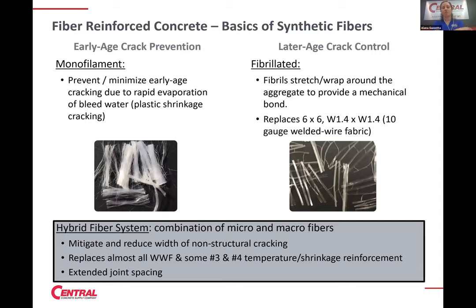These are things to look at in terms of weighing the options of putting synthetic fibers in a concrete mix versus having rebar and the additional transportation to the site, when looking at the project as a whole in terms of a whole-building LCA. The fibers on the left-hand side are very thin fibers used to help prevent very early-age cracking — something a contractor would choose to use if cracking is an important consideration or if you're pouring in a hot, windy environment. The ones on the right are fiber types that can replace welded wire fabric, and there's a hybrid system combining those small monofilament fibers with a longer tape-like fiber that lays flat for good finishing but allows it to replace welded wire fabric or number 3 and number 4 temperature reinforcement.